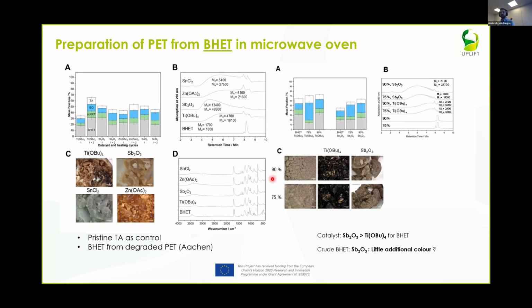Also, lower purity monomers were investigated. Here, it seems that we do only get a little additional color, and that seems to be directly related to the discoloration in the monomers when they're produced. So if we can get rid of the excess color from the monomer, it seems to be what coloration we have, mainly for the monomers. The titanium in this case gives a heavy discoloration for these systems.